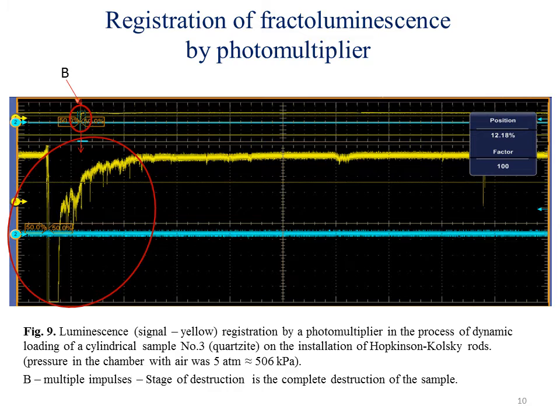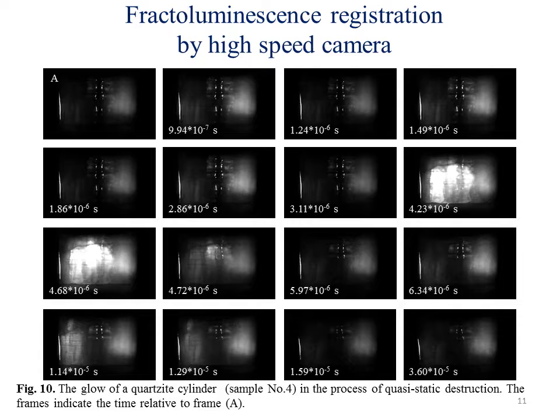With the help of a photomultiplier, the luminescence of sample number 3 was recorded in the process of dynamic destruction. The destruction was accompanied by a signal with multiple pulses. This is typical for destruction with the appearance of micro damages and their merging into macro cracks until complete fragmentation of the sample, followed by the fracture of the fragments themselves. The form of the fracture process under dynamic loading was similar to that observed for the fourth sample under quasi-static loading.